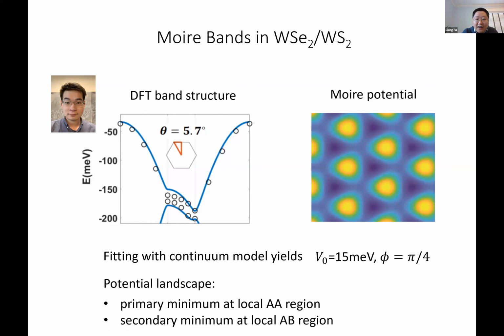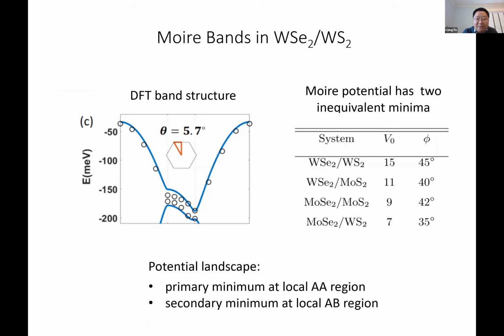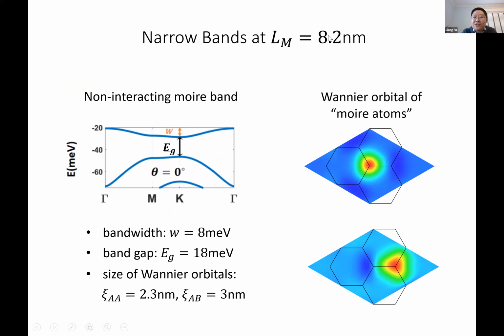So once we have extracted these Moiré potentials, this allows us to calculate the non-interacting band structure at larger Moiré period. With 8 nanometer periodicity, the unit cell consists of about 10,000 atoms, so it's impossible to do a DFT calculation. But now we can look at the continuum model with the parameters extracted from DFT at a smaller twist angle, a smaller period.